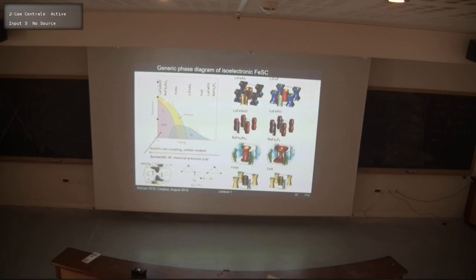There are other effects which give us the final ground state. Here I also have iron selenium, which is inside a nematic state, and its related compound, iron sulfur, is a low-Tc superconductor right here. Similarly for the lanthanum one, it is an antiferromagnetic metal, and if you put in the phosphorus, it's right here, low Tc.